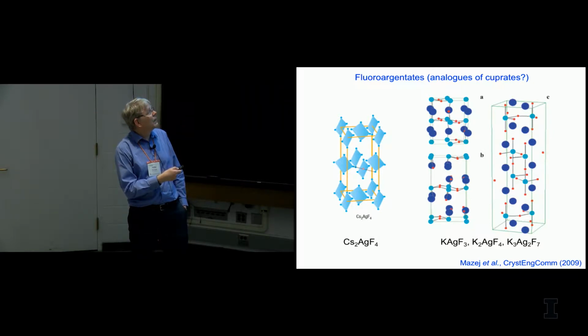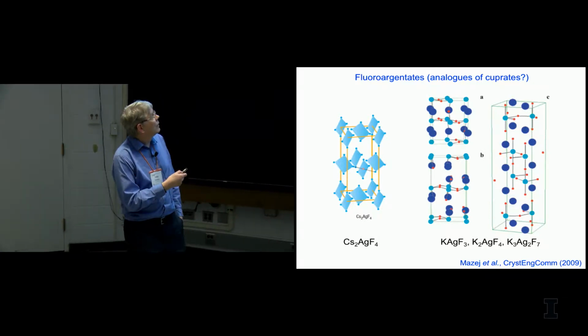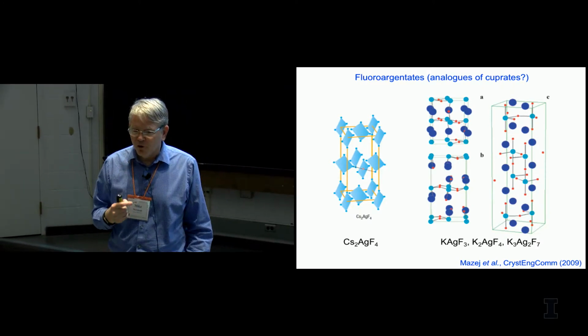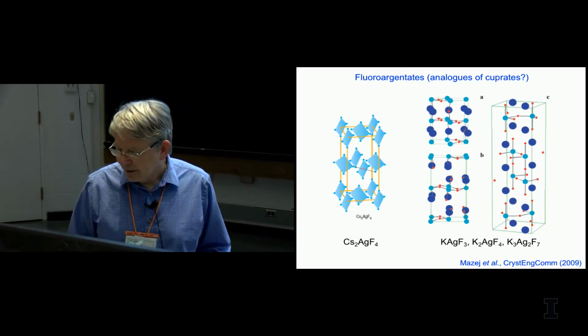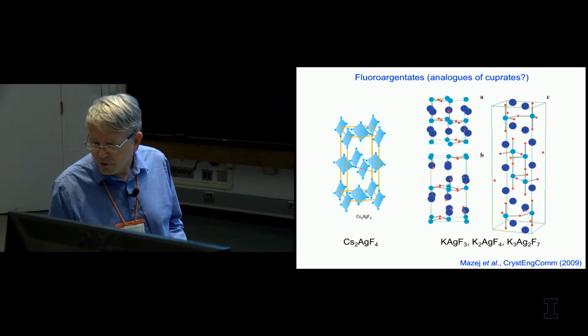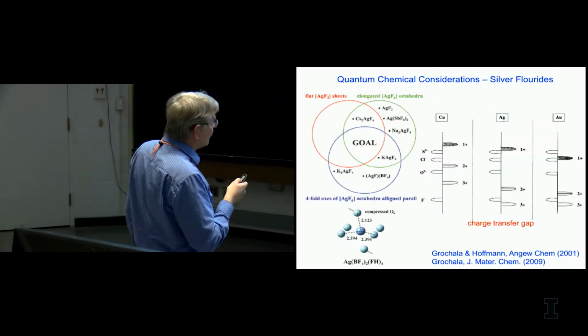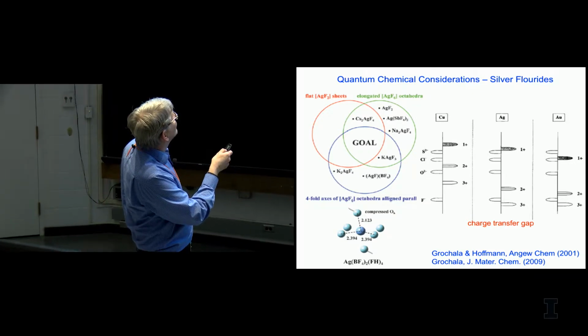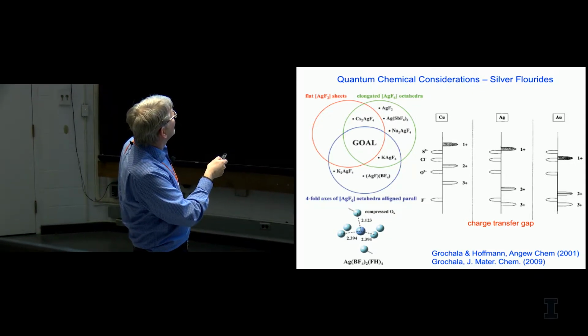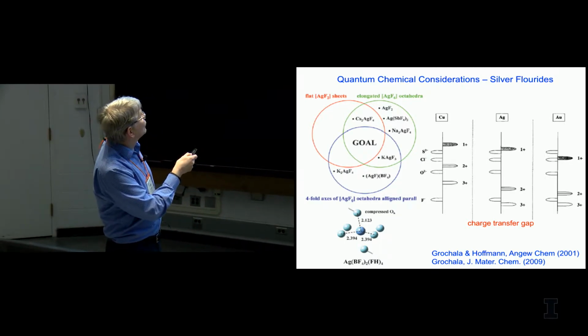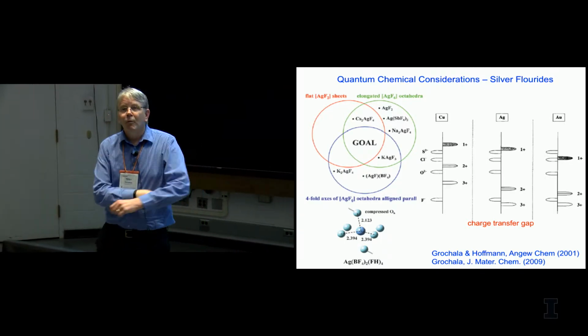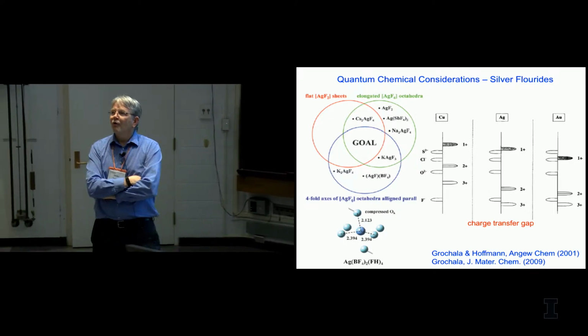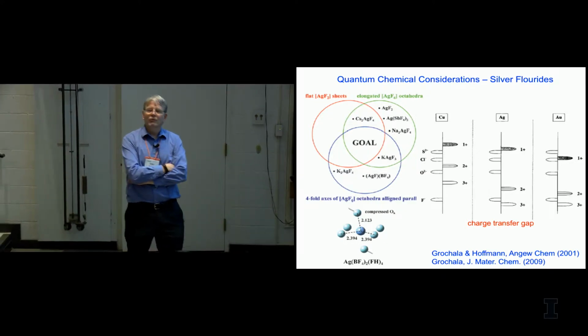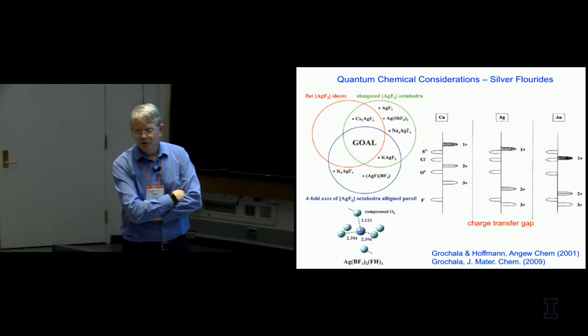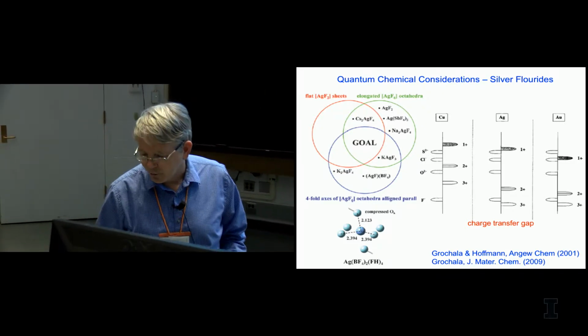The problem is getting these materials to form square planar nets is difficult because silver prefers to be in a d8 and d10 configuration and doesn't like to be in the standard type of Jahn-Teller environment that copper likes to be in. So if you look for the conditions of getting flat sheets, elongated octahedra, fourfold axis oriented along the c-axis, it's tough to get something in here. The proposals do this by MBE. I don't know if Jim Eckstein's in the audience, but Jim probably doesn't want to put fluorine into his MBE machine. But this has been the proposal for maybe realizing this class of materials.